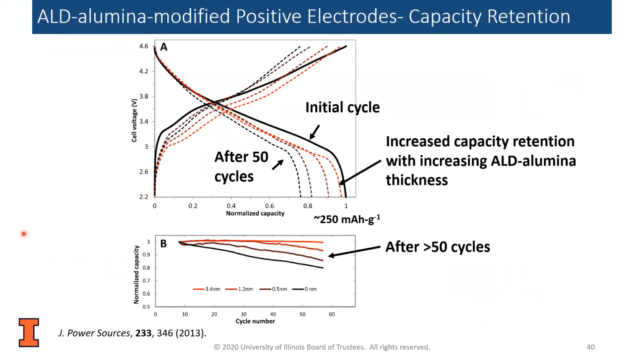So once we started studying the performance of these batteries, here's shown the initial charging capacity of the battery in the bold black, and each of these are increasing thickness, or I'm sorry, decreasing thickness. So we see that after 50 cycles, we have limited capacity as compared to the increased thicknesses. And you see the normalized capacity shows that as well. For the thinner layers, we found that we have less capacity overall as compared to the thicker layers. In fact, the thickest layer showed after 50 cycles a very minimum decrease in